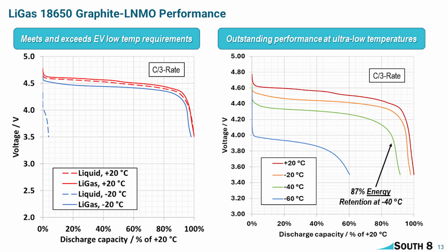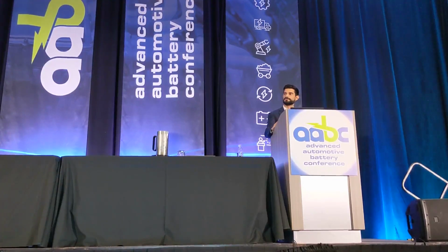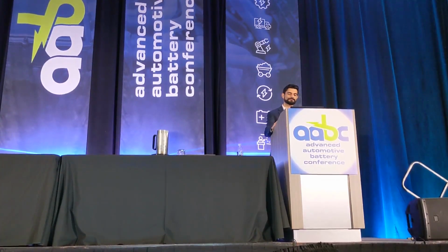But at -40 degrees Celsius, which is where a lot of the automotive industry would be, like the very minimum of the temperature range, we're still showing close to 90% of your energy retention. That's really, really impressive. It's essentially going to be working in any temperature you give it. So that's really a unique benefit of our chemistry here.